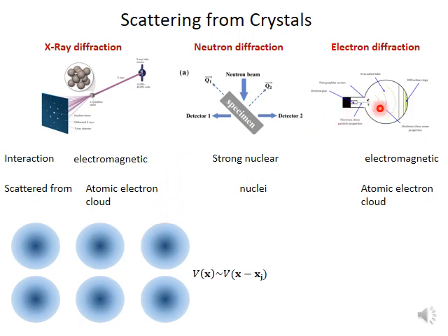If you compare it with incident electrons, if the incident electron is incident on such a crystal, it would immediately see this electronic cloud and would scatter from the electronic cloud. It won't penetrate much inside, but since X-rays have very large energy, much larger than the energy of the inner shell electrons, these X-rays can really penetrate the electronic cloud inside.